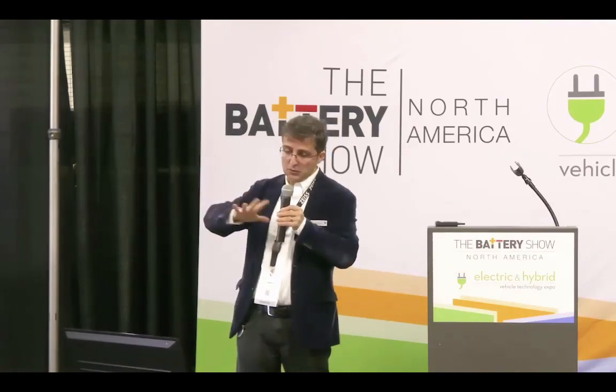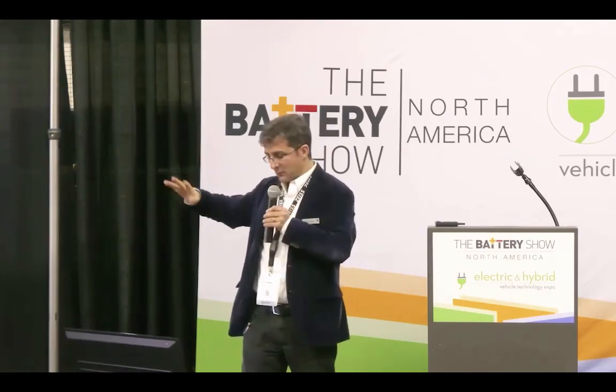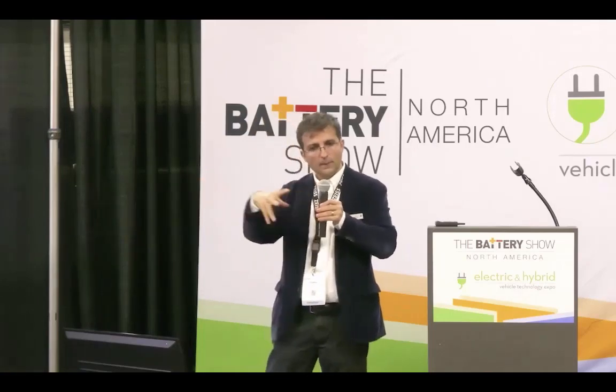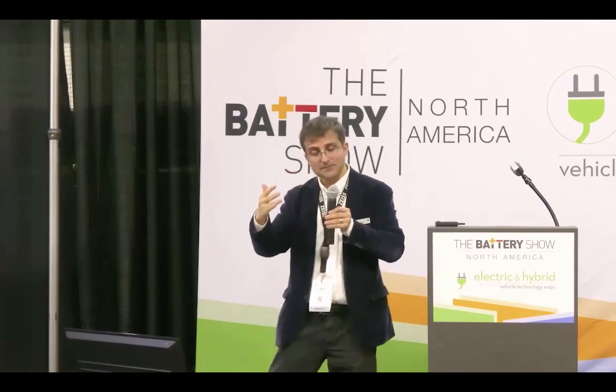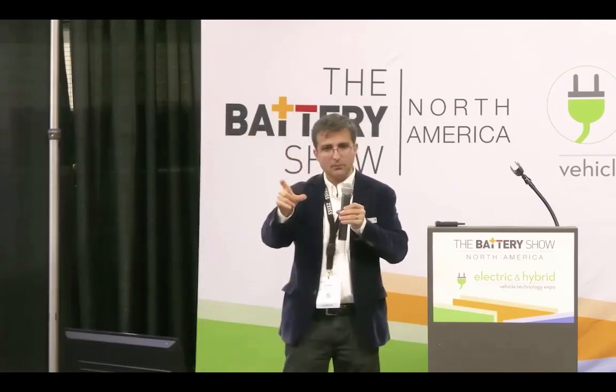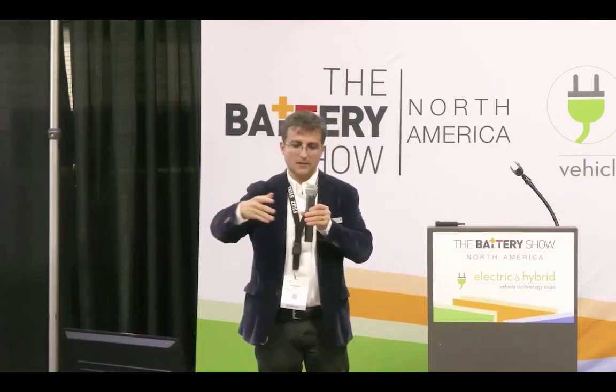I will say, if you use high kV systems, it's great for general assembly, in terms of how the battery is inside, and maybe some overhang, but you will not be able to see at the particle level. To do that, you need to use a smaller sample and then use 160 kV with optical magnification that gives you that higher resolution. So it's basically a balancing game between the different limitations of the physics of X-rays and the size and material of the sample.